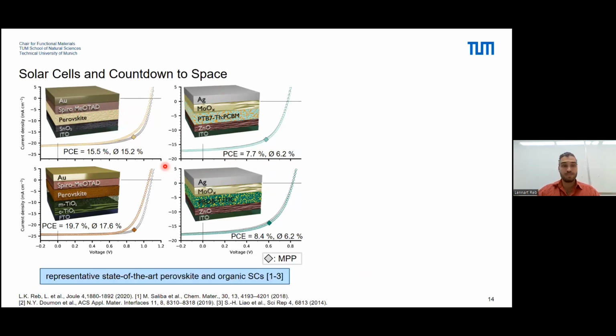Okay, these solar cells in the pre-test achieved an average efficiency of around 15 to 17% for the perovskites, and around 6% for the organic ones. At the time of the rocket flight, these were quite good and therefore representative state-of-the-art perovskite and organic solar cells.